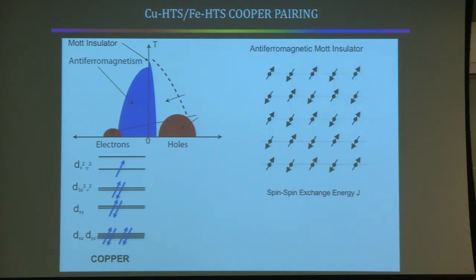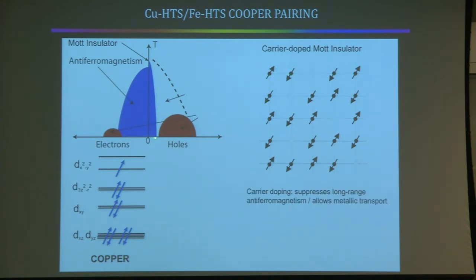So let's just think about the copper case. We have a reasonable understanding of the copper case. Okay, it's a Mott insulator. The on-site Coulomb interaction of this electron prevents double occupancy, and so all of these electrons are localized. Second-order superexchange produces a strong magnetic interaction between adjacent spin-half electrons. When you carrier dope this, especially with holes, it does two things. It suppresses the antiferromagnetism, and it allows metallic transport and superconductivity.